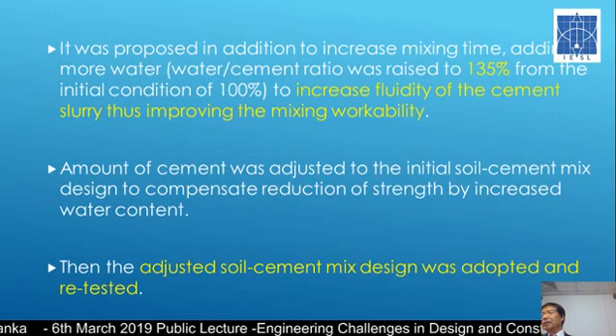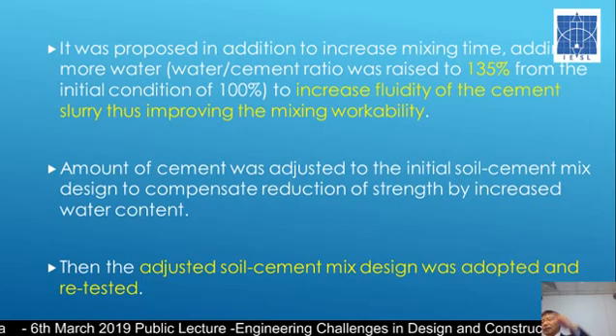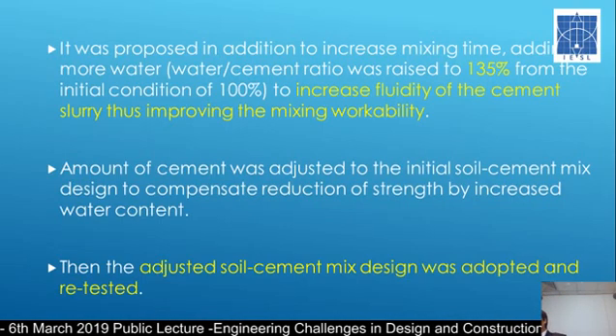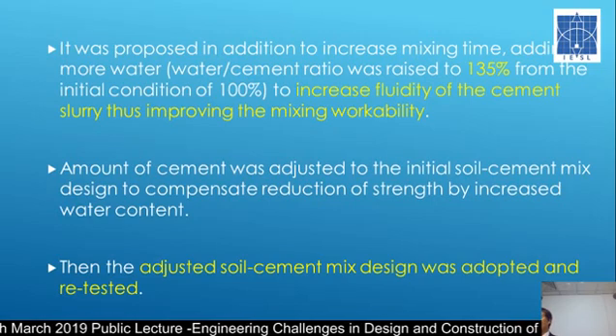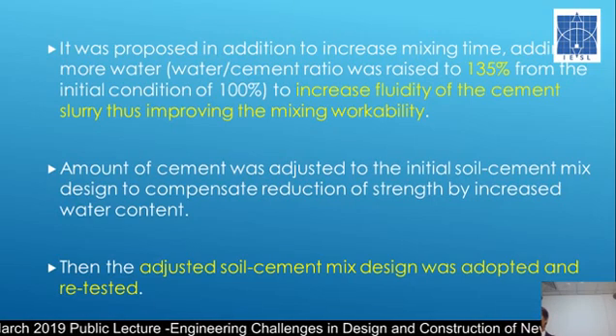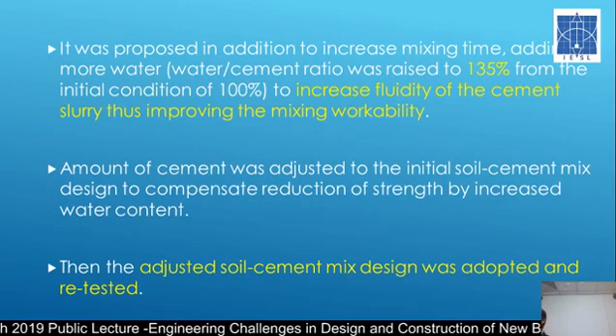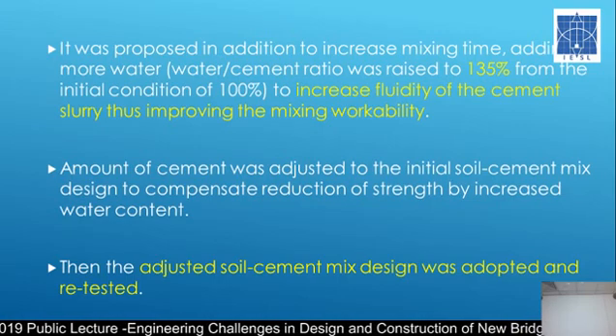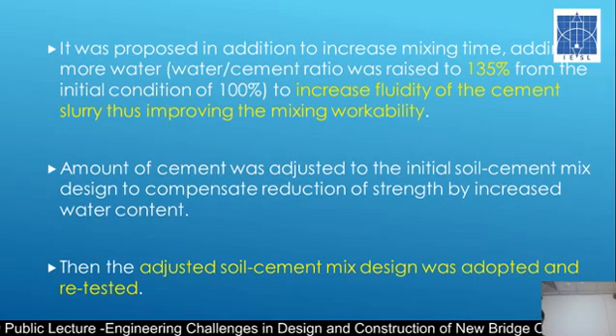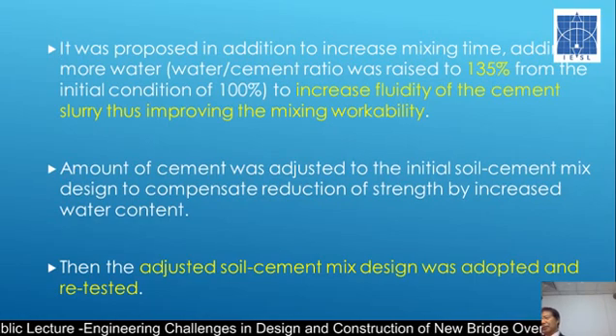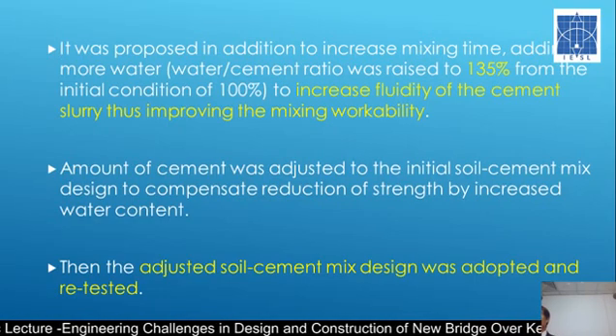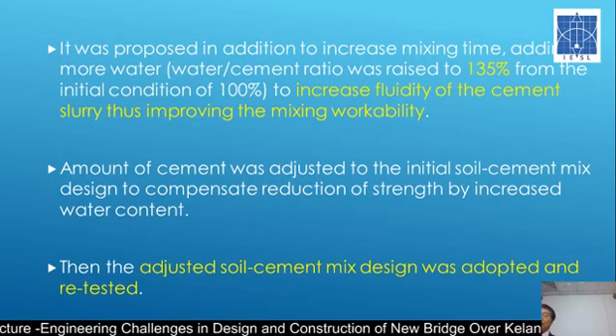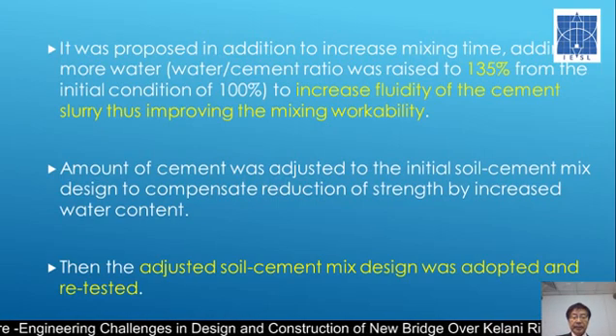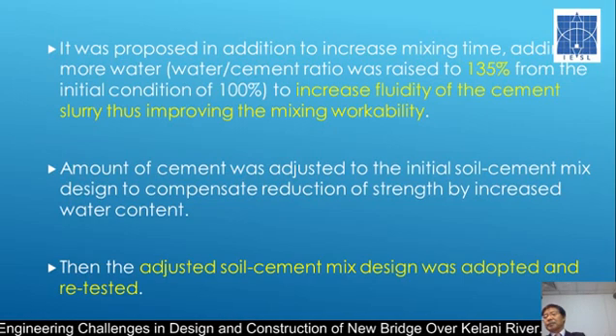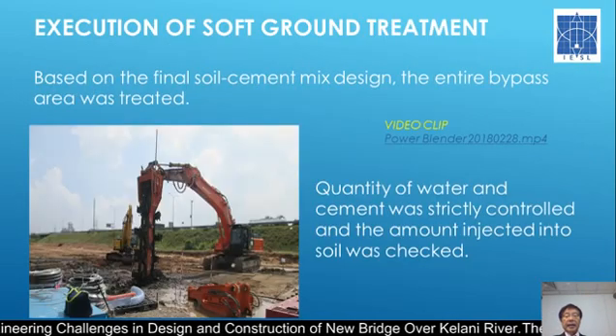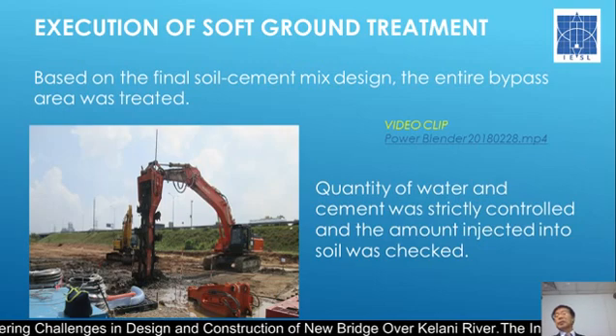And we found that it is because mixing about 10 meters of soil uniformly is not achieved by the water cement ratio of 100%. So we increased the water to make the soil and cement more fluid, and also because when you have more water, that reduces strength, right? So we have to adjust the cement ratio. So we did a lot of exercises, and finally we got a good solution.